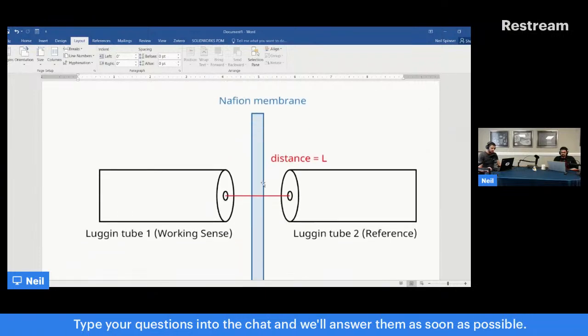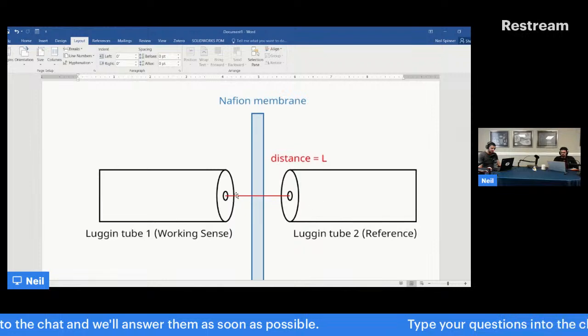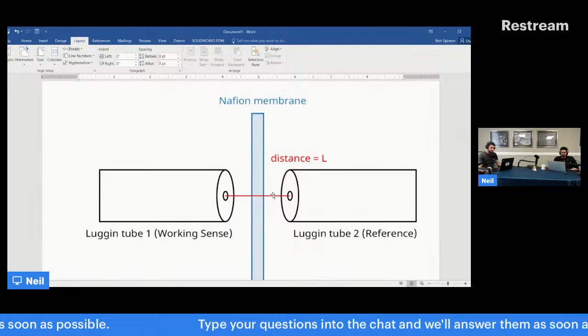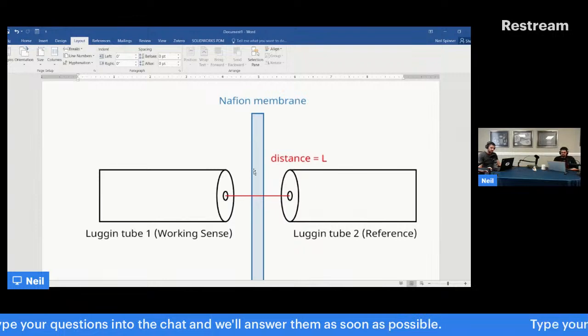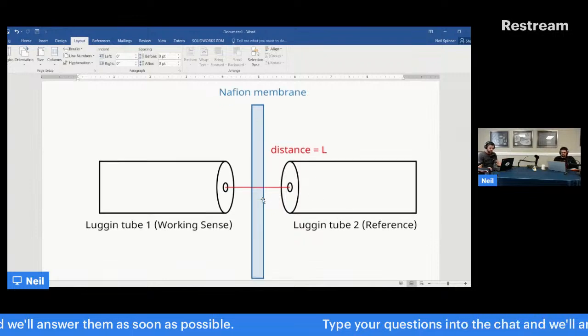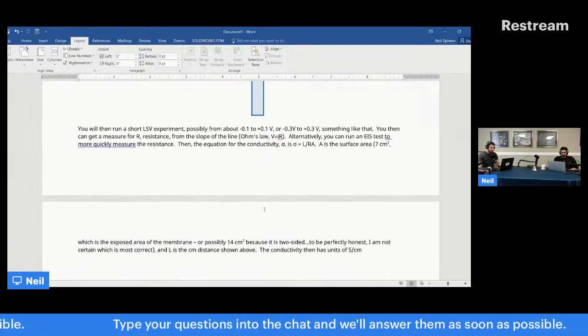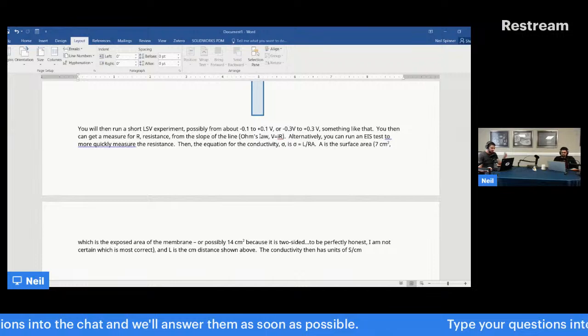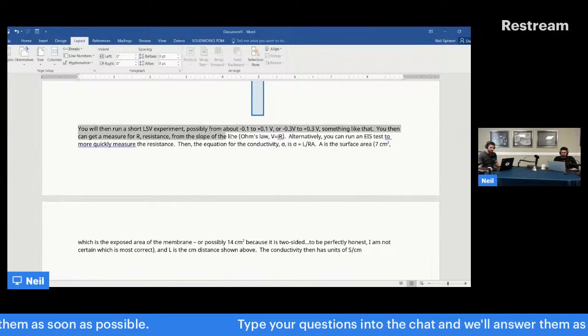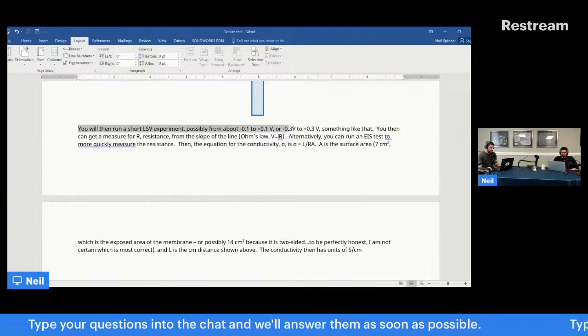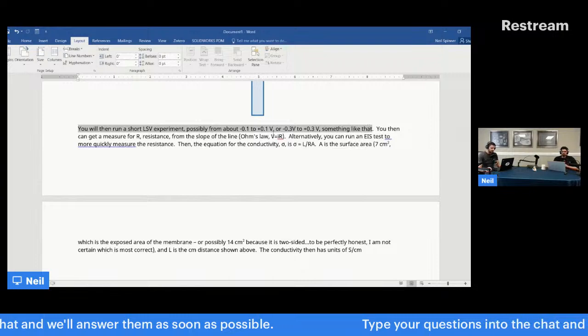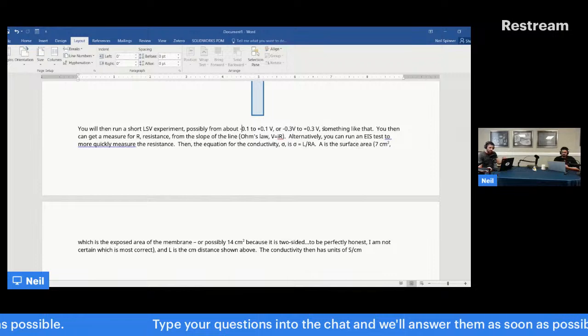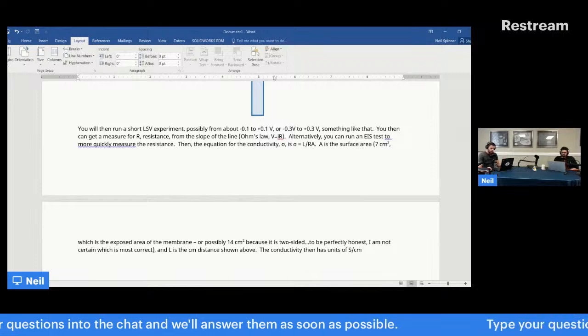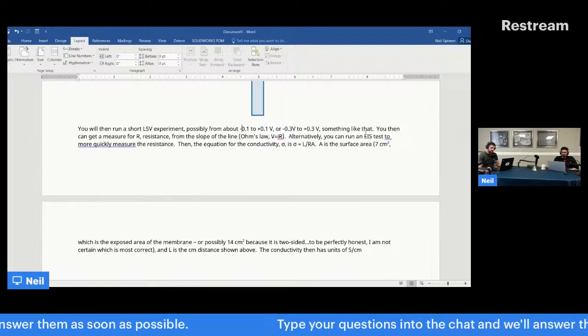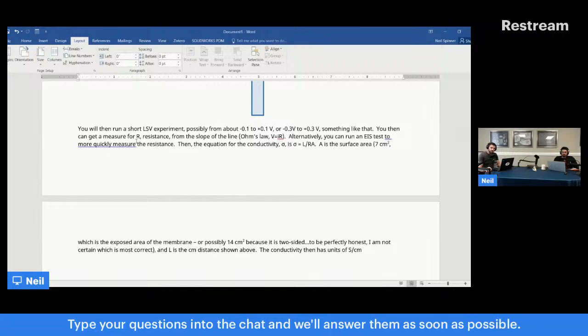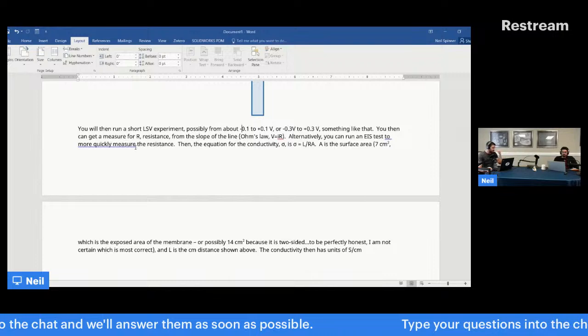And what you're doing is effectively, this is the cross section here. So you have your Luggin tube. You want to get an estimate of the distance between the two Luggin tube openings, and you have your Nafion in between, and there's solution everywhere, like sulfuric acid. The way this is done in theory is one of two ways. This is from an email I've sent to people before. You can run a short LSV experiment, something like linear polarization resistance. Around OCP, you go 100 millivolts, or 200 or 300 millivolts, up and down. It hopefully makes a straight line, and from the slope of that you get the resistance. Or you do an EIS, and probably somewhere at the high frequency range you would get the ohmic resistance, and that would be it.